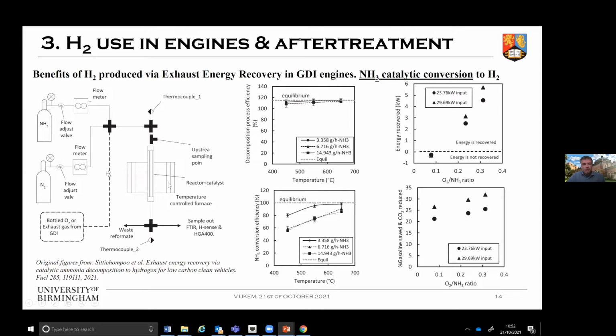And then to finish today, again with the topic of spark ignition engines, we did some preliminary work on the case of ammonia. We studied the dissociation, the cracking process of ammonia, by using the exhaust of a gasoline direct injection engine. What we obtained is that we were able to recover some waste heat. Efficiency here higher than 100%, in the way that we define it, means that we are able to recover waste heat from the exhaust. We were also able, depending on temperature, to convert ammonia to hydrogen more or less successfully. When we increase temperature, we were able to increase the conversion to hydrogen.